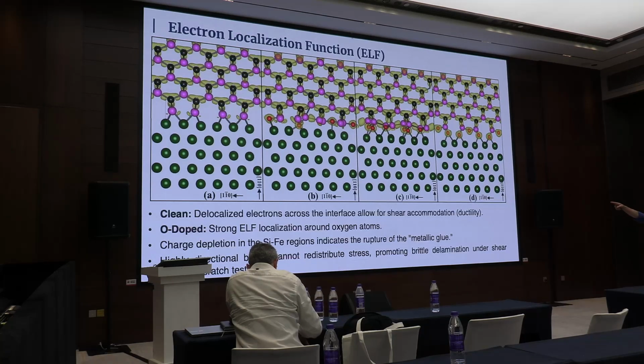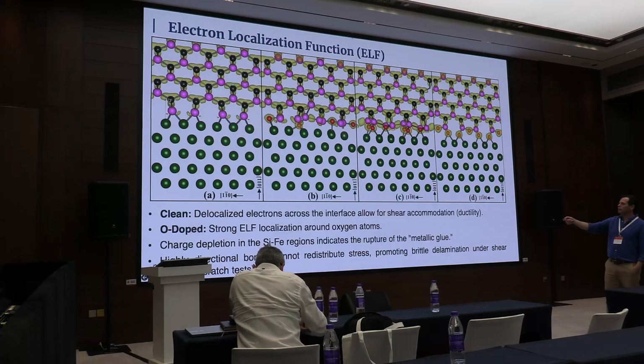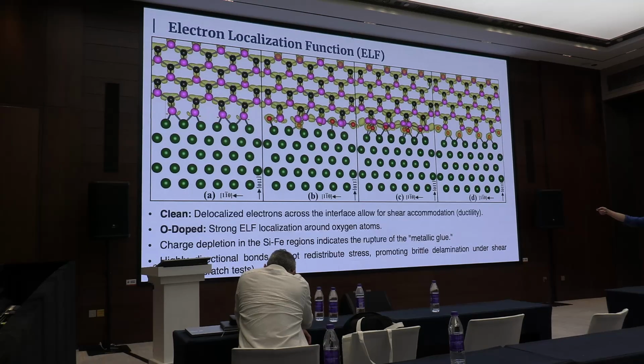So, without oxygen, we can see how this electron density is plotted around the bonds, and this is a plastic behavior. And as soon as we start to have more oxygen, we change from covalent bond to ionic. This is here, an ionic interaction in between iron, oxygen, and silicium. This is how the glassy situation is emerging.